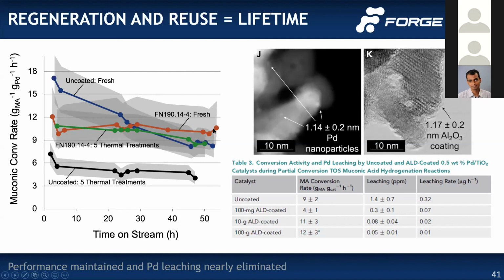So being able to maintain your catalyst through regeneration is one of the benefits of overcoats. The other benefit here for this example was that we could actually stop leaching of palladium off of the surface. This is a very big advantage as well, so you're not losing your active material to the process.